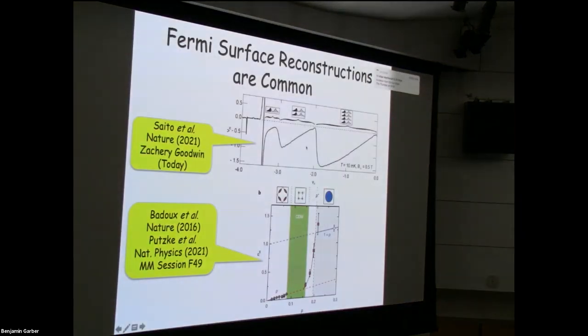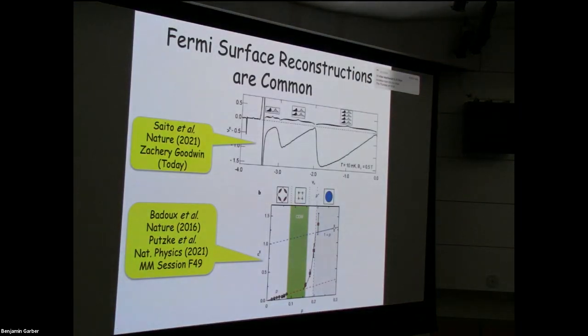What you see at the beginning, starting from neutrality, is you make holes in the flat valence band. You start to get a bigger and bigger hole-like Fermi surface. This is Hall density as measured by the Hall effect, expressed as a filling factor. So that's just what you expect, and then you get this unexpected feature in which the size of the Fermi surface remains hole-like, but its size resets to zero.